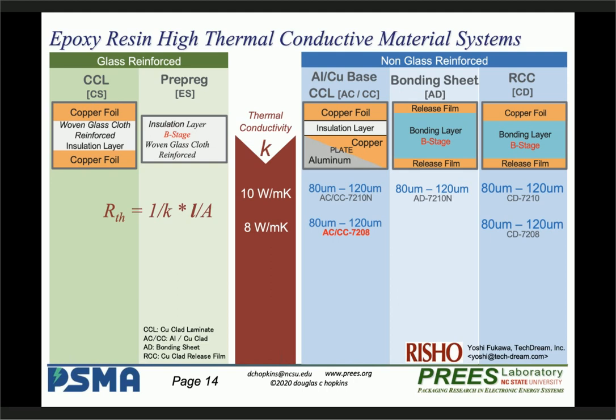What we're interested in is their top line performance, which is they have materials now at up to 10 watts per meter-degree K. We did a lot of the research. If you look at our publications, they're done with 8 watts per meter-degree K. And with 8 watts per meter-degree K at 120 microns, we perform thermally better than alumina DBC. So if you were to do, let's say, 8 mils of copper, 25 mils of alumina, and 8 mils of copper, the alumina of 25 mils, 625 microns, performs a little less well than this 8 watts per meter-degree K, 120 micron organic material. So we can beat alumina.